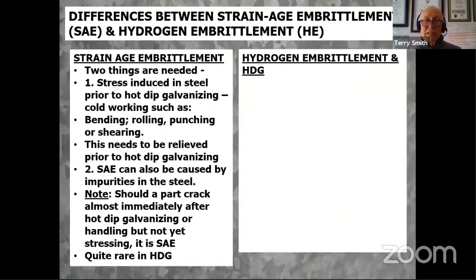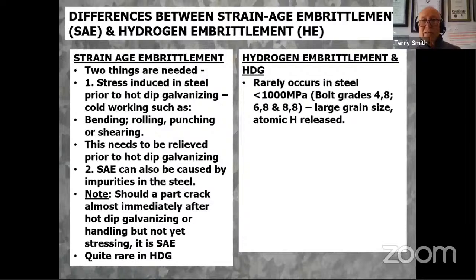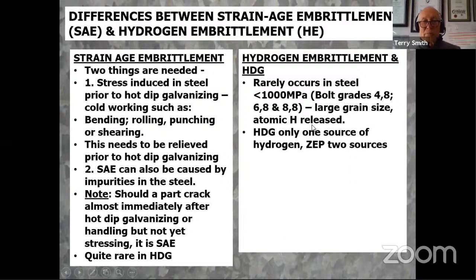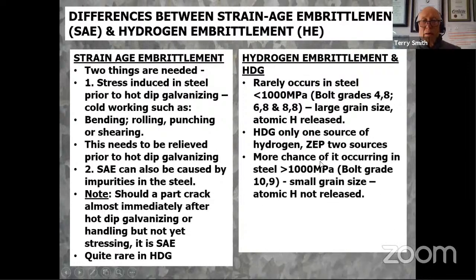This is hydrogen embrittlement. Hot dip galvanizing, it rarely occurs in steel less than 1,000 MPa in strength, and that includes bolt grades 4.8, 6.8, and 8.8. It has a large grain size, so atomic hydrogen is released during the process. Hot dip galvanizing has only one source of hydrogen, and that's in our cleaning liquid. Zinc electroplating has two sources of hydrogen. There is more chance of it occurring in steel greater than 1,000 MPa, which includes the bolt grade 10.9. It has a small grain size, and therefore atomic hydrogen is not released.